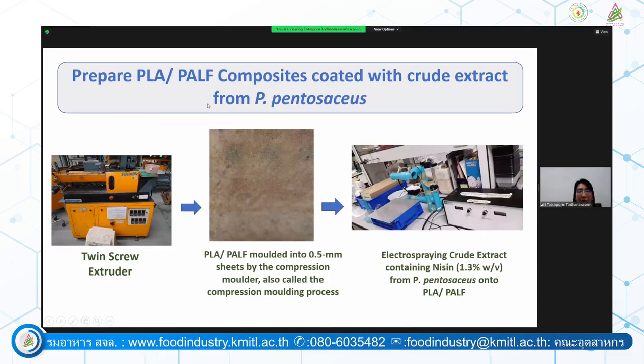After we get the pineapple fiber, we take it to a machine to make it into powder, small enough to put into the twin screw extruder. For this twin screw extruder, we used the machine at MTEC in Thailand. They are good at making nanomaterials and material science. Inside the twin screw extruder, we mix the polylactic acid pellet with the powder of the PALF. Once it comes out of the twin screw extruder, we get pellets of the mixture of PLA and PALF. After that, we melt it and make it into a sheet using compression molding, with a thickness of about 0.5 millimeter.